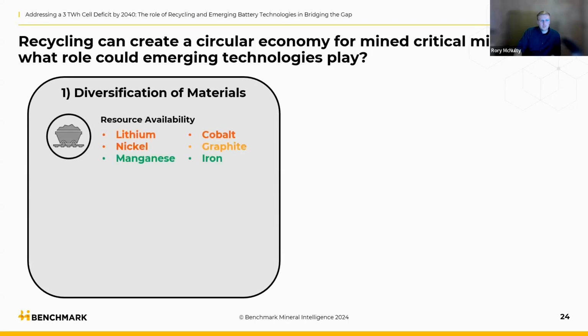If we look at traditional lithium-ion batteries, what we see is that lithium, nickel and cobalt, as shown by Beatrice earlier on, are all forecast to enter a market deficit before the turn of the decade. The graphite itself on the anode market, although it has a more balanced supply demand beyond 2030, we see other geopolitical risks, with China currently dominating more than 95% of that midstream graphite anode market. Diversification here will be needed on globalization in order to alleviate some of those geopolitical constraints. And then you have other materials like manganese and iron, which are used in cathode chemistries for lithium-ion batteries, with highly established industrial use cases where refining could be a bottleneck, getting the purity required to produce those materials, but much more abundant and much more sustainably sourced.